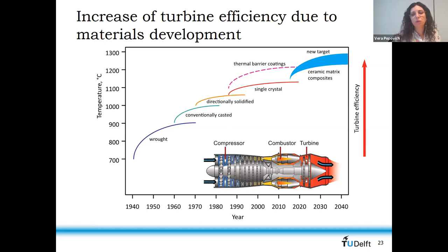And if we look at this century, from the 2000s to 2010, that for sure was the age, from the mid 90s, let's say, when thermal barrier coatings were applied and pushed the possibilities of current materials even further. With the application of thermal barrier coatings, which can be different ones, you can push the temperature inside the bulk, so inside the turbine blade, for example, up to 150, 200 degrees.